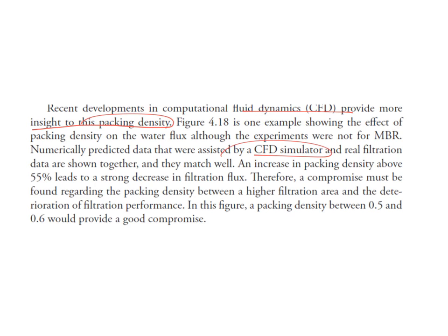Using CFD simulation and comparing it with real experimental data, we can optimize the module design. There are a lot of studies on this, and according to one example, a packing density between 0.5 and 0.6 can provide a good compromise.